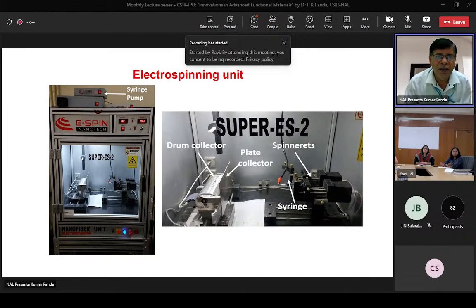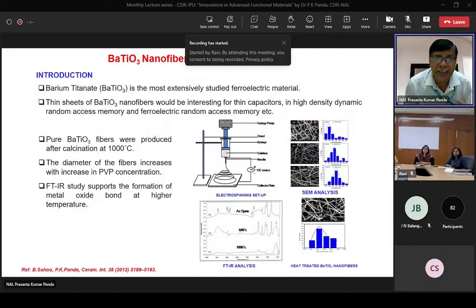Then after coming here, we got this facility, an electrospinning unit, and we have a multiple electrospinning unit to prepare our membranes for various applications. What is interesting here is that because of the nanofibrous nature, it has a high surface area to volume ratio and is very good for various sensing applications. In our initial years, we prepared not only polymer nanofibers but also ceramic nanofibers, even piezoelectric ceramic nanofibers. We successfully prepared barium titanate nanofibers by electrospinning, published in Ceramics International. I'll not get into details. You take the precursors of barium titanate and PVP as the polymer vehicle and do electrospinning to generate the fibers, and after heat treatment, you get the nanofibers of barium titanate.